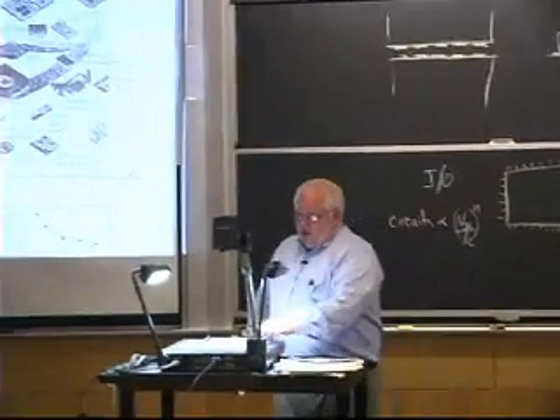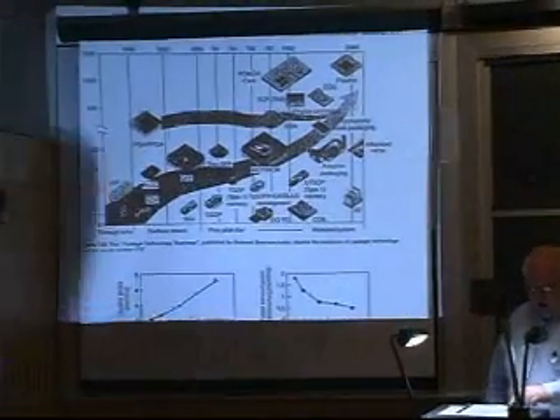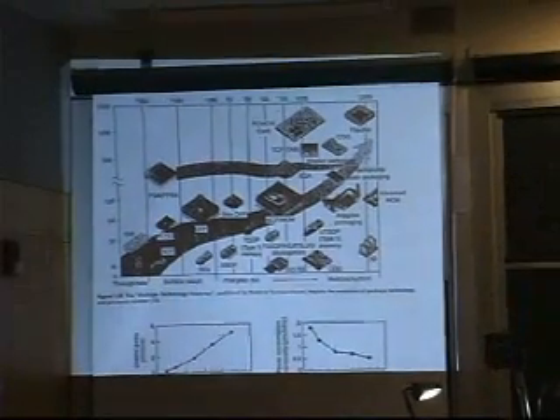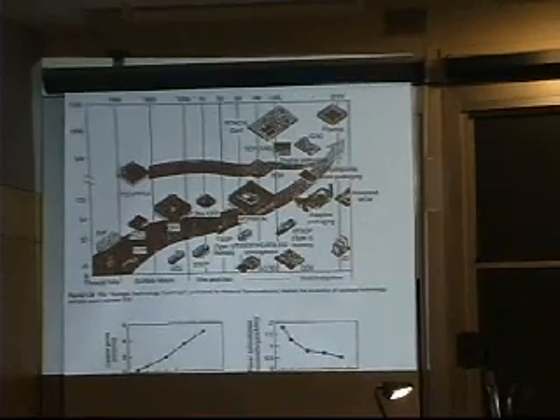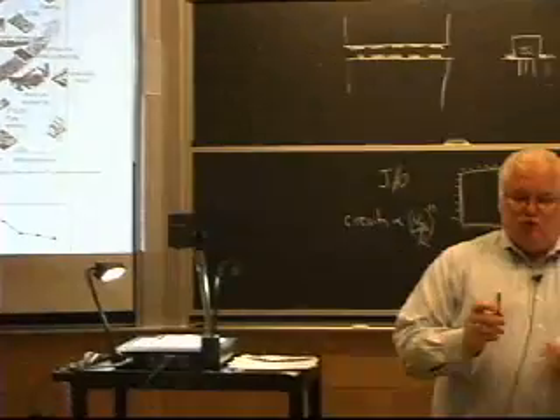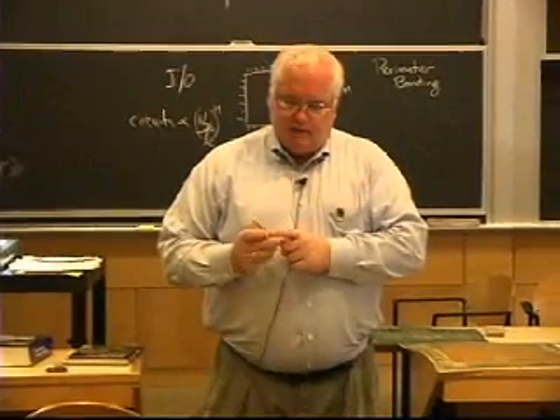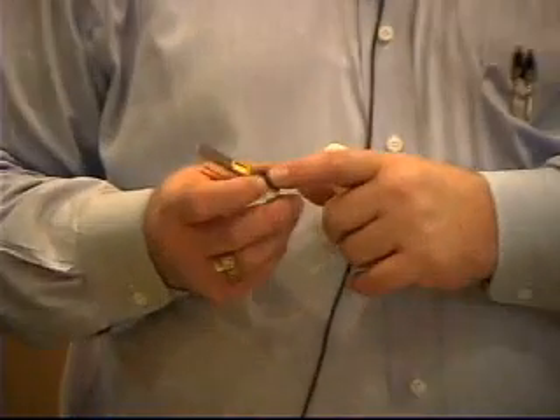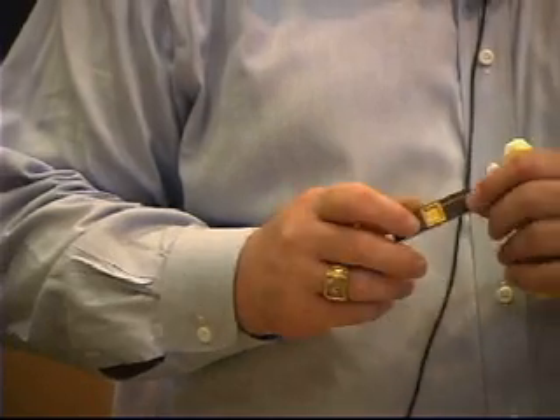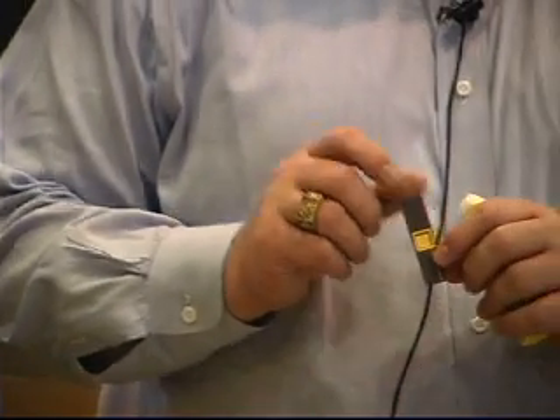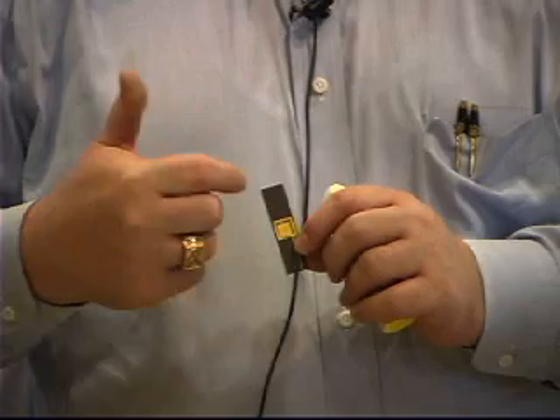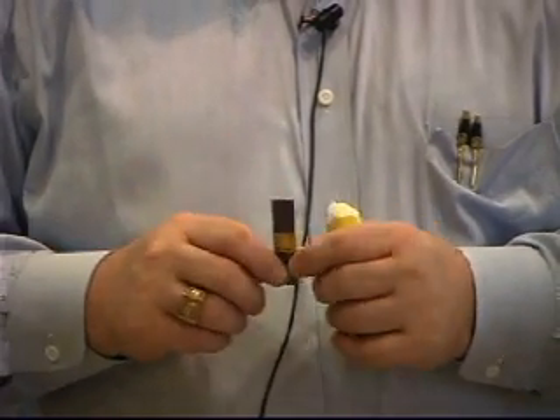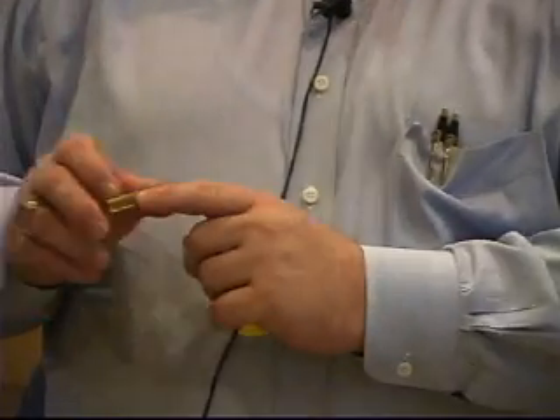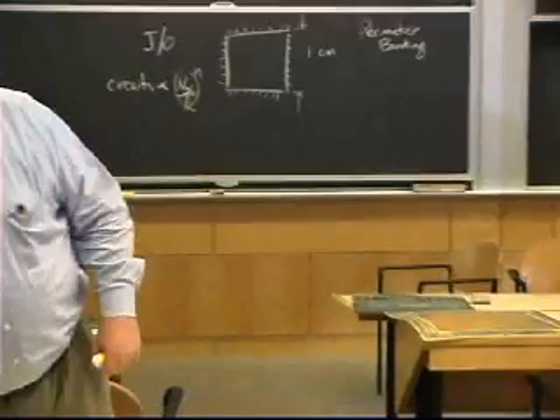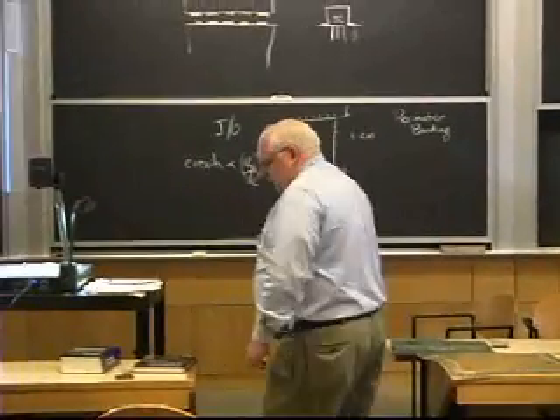Well, if you look at time here across the top, in 1980, we were down here with like 16 or 32 inputs and outputs with a DIP. They call it a DIP? Yeah. DIP. Here's a DIP. It's an aluminum oxide. Actually, it's dark because it's about 94% aluminum oxide, and it's got about 6% manganese oxide. It's a ceramic, and if you could cut through this thing, you'd find the whole thing is metallized with gold layers or tungsten layers, typically tungsten, I guess. Tungsten layers, and you have this number of inputs and outputs along the side, right? So there's a chip carrier, kind of 1980 style.